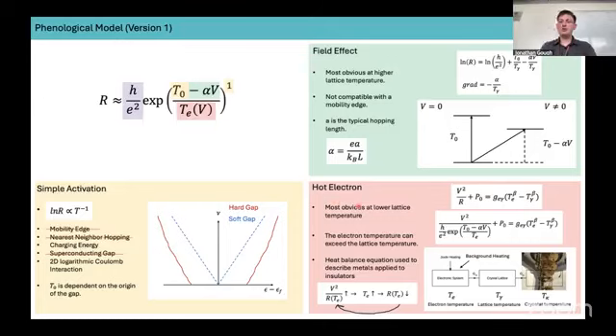So we assume we have this weak electron-phonon coupling. By doing this, we assume that the heat balance equation used to describe dirty metals can be applied to insulators. So essentially you're equating your power in, say your joule heat, V squared upon R, with your power provided to the electrons and then taken away by the bath.